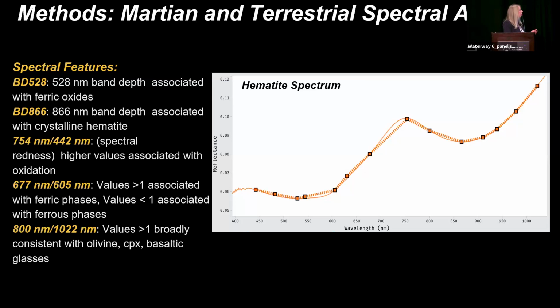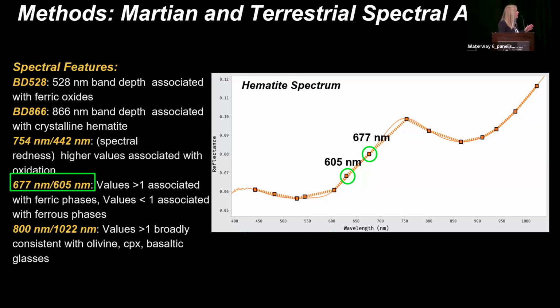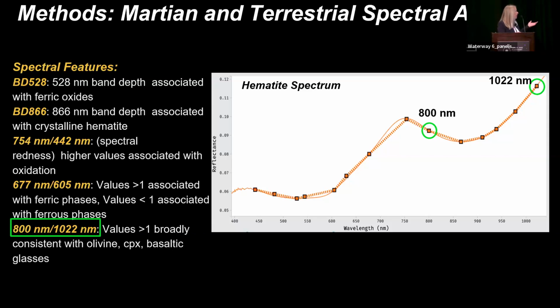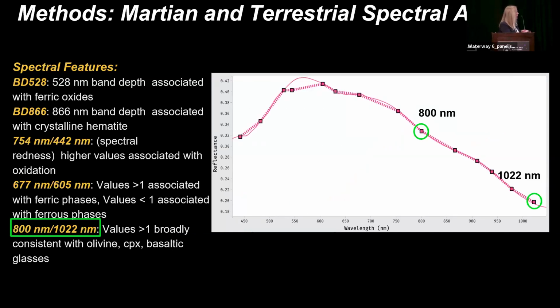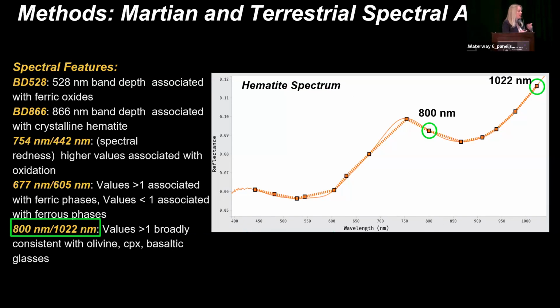So the spectral features that we were using for our analysis were the 528 nanometer band depth, which is associated broadly with ferric oxides, BD866, or the 866 nanometer band depth, which is associated with crystalline hematite, the ratio of 754 over 442, which we call spectral redness, where higher values are associated with increased oxidation, the ratio of 677 nanometers over 605 nanometers, where values greater than 1 are associated with ferric phases, and values less than 1 are associated with ferrous phases. And finally, the near-infrared ratio of 800 nanometers over 1022 nanometers. So here, values greater than 1 are broadly consistent with olivine, as you can see in this figure, and values less than 1 can be interpreted sometimes as iron meteorites, although we haven't observed those in Jezero Crater. But with a combination of this value and other values, you may also be looking at a hematite spectrum, as we are in this figure.